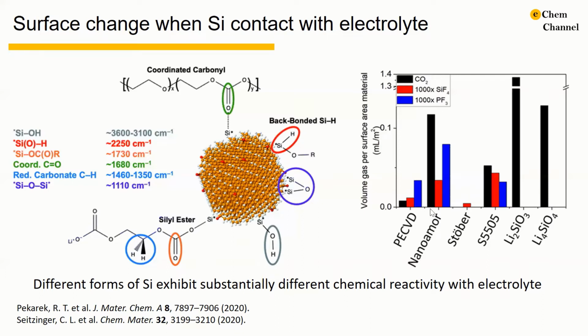And other work examined the released gaseous components when the silicon electrode is exposed to the electrolyte. Silicon compounds and lithium hexafluorophosphate salt produce a significant amount of gas when combined. The gas released includes carbon dioxide, silicon tetrafluoride, and phosphorus trifluoride gases. They find that the gas-forming reactions are highly correlated, where one decomposition reaction leads to a subsequent decomposition reaction. Compared to the silicon powder and the silica, the surface with high lithium content seems to be the most passivating to gassing reactions, so it only releases carbon dioxide.